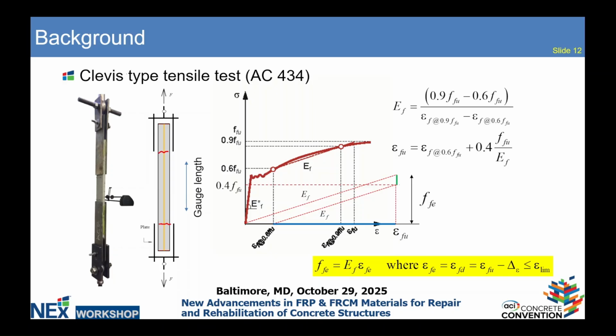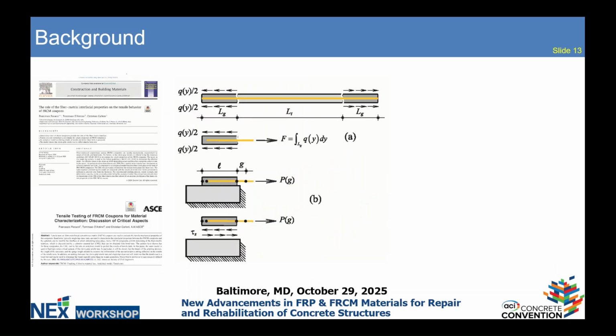I should mention that in any of these tests, regardless of how long the coupon is, the first thing you see is two cracks where the plates are, and then depending on how long the free part of the coupon is without the plate, you might see one in the middle, two more, and so forth. So what we have shown is that analytically, we did a little bit of work with my colleague, Professor Dantino and Professor Focacci, that the clevis type top part basically is nothing more than a single lap bottom part, where the plates, the steel plates, act as the substrate, and basically the section where you have the crack in the matrix is the end section of the single lap test. So really what you are testing is a single lap test, and all depends on the length of the plates.